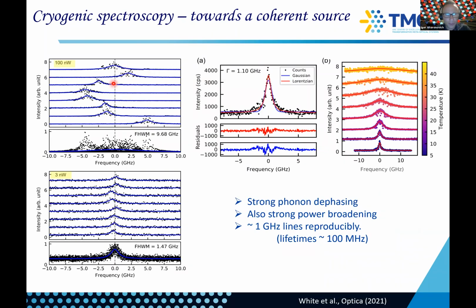So the way to combat this spectral diffusion, and you can see it here, is really to try to reduce the power to the minimum. And so this is now about 3 nanowatt excitation, again on resonance. And so now you can get a nearly coherent source, so 1.5 gigahertz. So our lifetime limit is about 100 megahertz, so we are only a factor of 10 away, which is already quite good. And so this is the line. It's still broadened, most likely by phonons, but nevertheless, at least stable. So for some applications, 1 gigahertz is good enough. Obviously, if you want to do two-photon interference, not quite there yet.